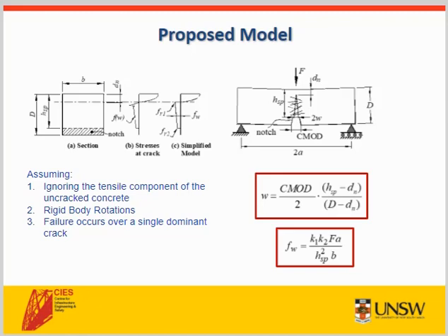Using mechanics, we also derived an expression for the residual tensile stress carried by the fibres as a function of the applied load and the geometrical characteristics of the specimen. It's important to note that these expressions can be used for any size prism.